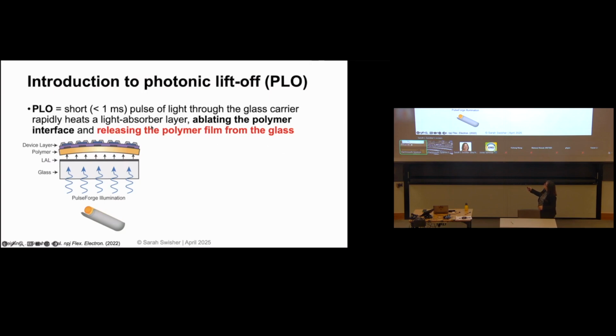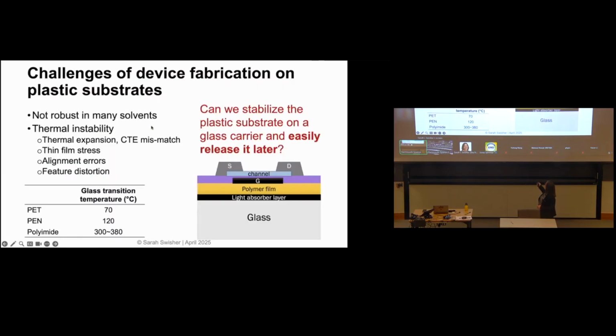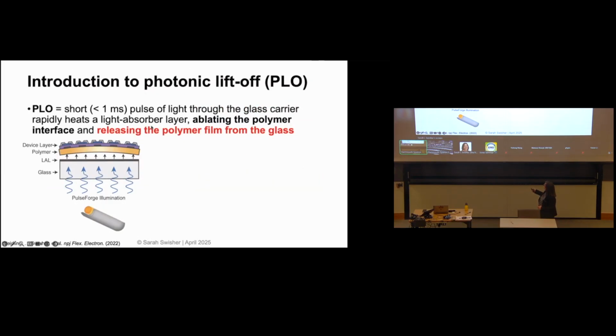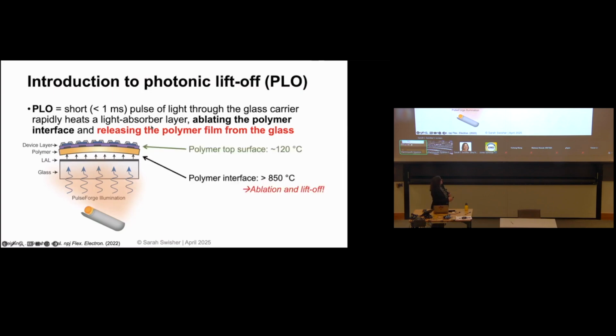So what it's going to do is get absorbed in this light absorbing layer, heat the interface of the polymer and that metal. Remember, it looked like this. So if I can heat that interface, I can actually ablate the polymer, turn it from a solid to a gas, right at the interface, and it's going to allow that polymer substrate to pop right off. Okay? So this illumination through the glass allows us to do that without affecting this device on top at all. So what we found is that the polymer surface where the devices sit is only going to be about 120 degrees, but this interface here is going to be about 850 or 900 degrees, and that's enough to vaporize that polymer and release it completely from the glass.